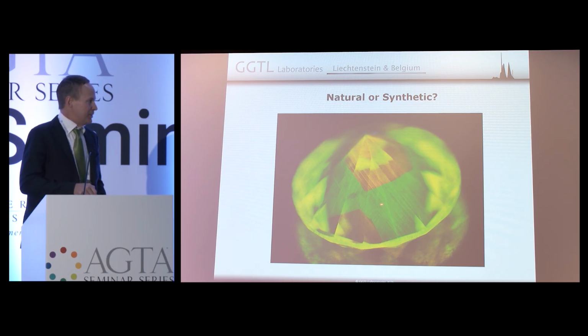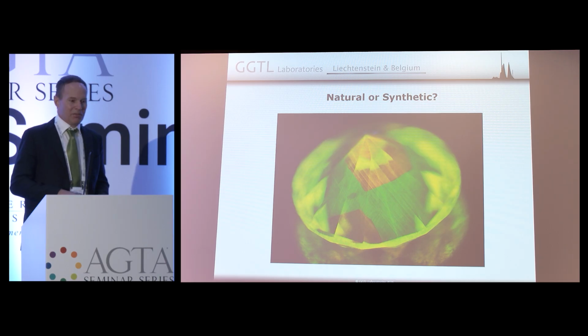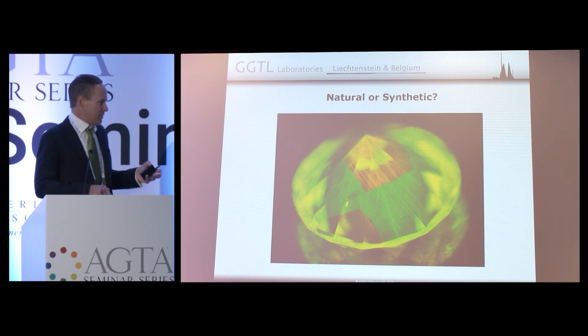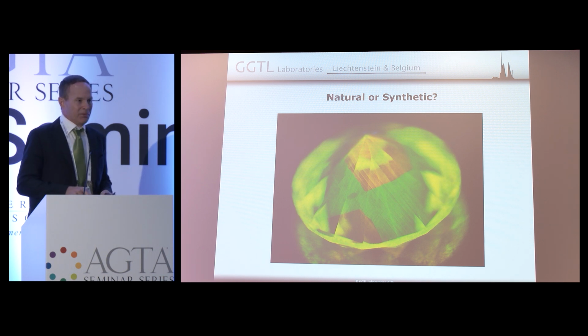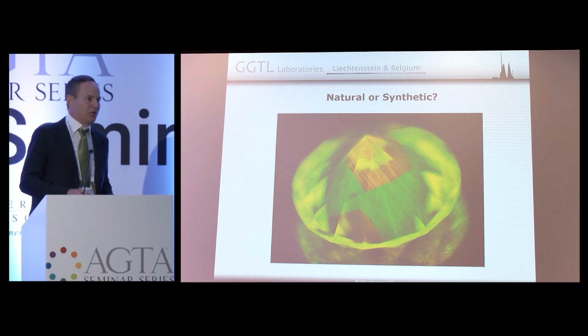And then what gives the answer in the end is at what excitation it looks best. In this specific case, this stone had the strongest features under shortwave UV and much less so under deep UV. For us, that gives a good indication. It doesn't always work because there are synthetics that behave similarly. But you look at this and you turn the stone around, you turn it in all directions, and with experience, you know that these things are actually natural. Whenever you have a doubt on a stone like that, you just take an infrared spectrum, and from there you usually know.